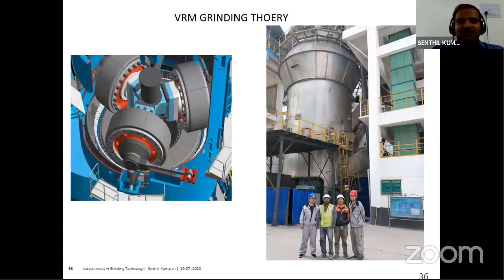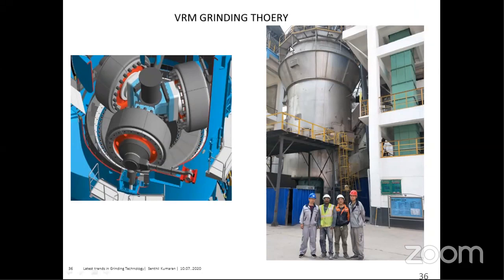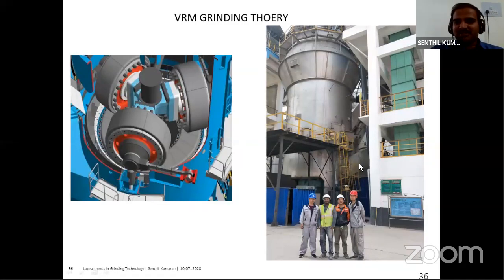So that's the advantage. And answering the previous question, atmospheric condition or isolated: as we can see, it is in the atmospheric condition only. But inside the mill, it will have its own setup. Here we can see the duct. This is a hot duct, where hot air enters. The inlet temperature of the mill will range from 200 to 400 degrees Celsius, and the mill outlet will be 80 to 98 degrees Celsius. The suction will be higher because the material has to be lifted throughout the mill and taken to the separator. As high as 1000 water column pressure will be maintained inside the mill.